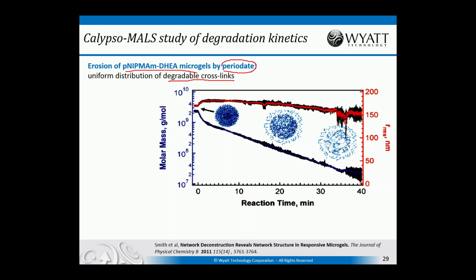And you can see conceptually what's happening. We're starting with a dense polymer at early time, and then the outer polymers are degraded, the links are broken, and it becomes a little diffuse. And then finally, the periodate diffuses inside, and the links break up throughout. So what do we see?